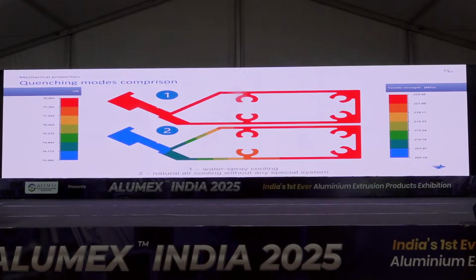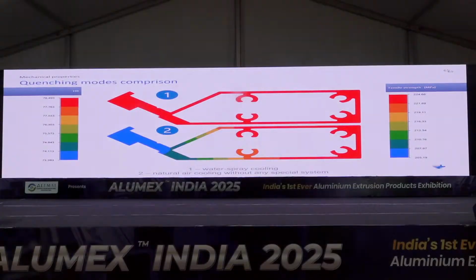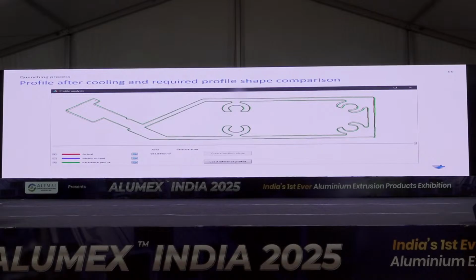Mechanical properties also can be predicted using the software. Once we have a good cooling rate, we will not end up with a huge non-uniformity of the mechanical properties distribution inside the profile. If it is not that good, you will have some non-uniformity, like in the second case. Also, you can check the section itself after the process.